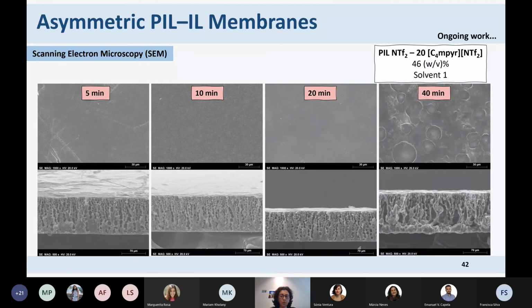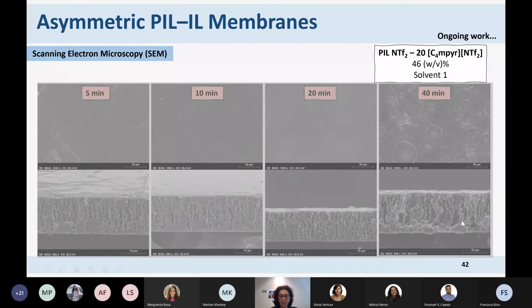And now let me show you the pictures. This is the time being exposed to the air before going inside of the bath, forming the dense layer, for 5, 10, 20, and 40 minutes. And what we can see here is that we have the creation of porosity inside of the membrane. This is the top. They are all dense. And we have the creation of porosity inside the membrane.